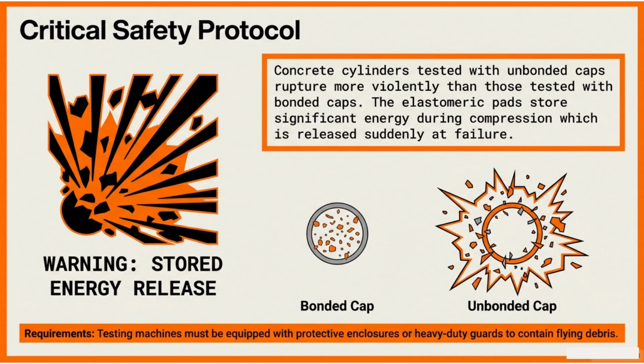Team, this slide is not optional. This is the slide that keeps people safe. When we test cylinders with unbonded caps, the failure can be more violent than with bonded caps. Why? Because the elastomeric pad stores energy during compression, and when the cylinder fails, that stored energy can release suddenly, almost like a spring snapping back. That's why you see the warning, stored energy release. Look at the illustrations. A bonded cap break is typically more predictable. An unbonded cap break can eject fragments more aggressively.